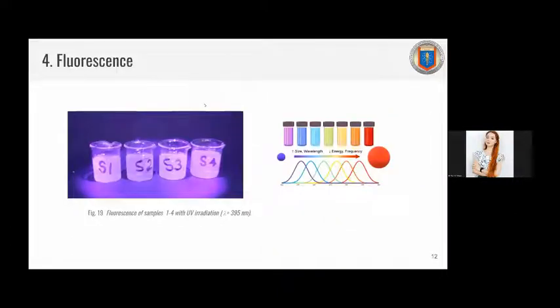Another way to prove that the quantum dots were present in the material was the qualitative fluorescent test, which was carried out with a wavelength of 395 nanometers, and the light source was only a UV light source irradiated towards the samples. And we could see there was a violet coloration observed in the 4 samples, something characteristic for quantum dots of a very small size.